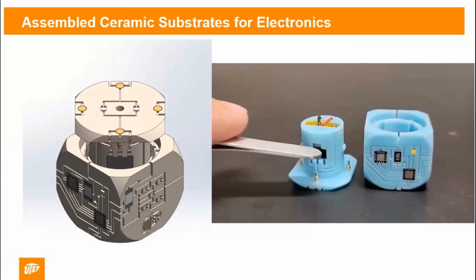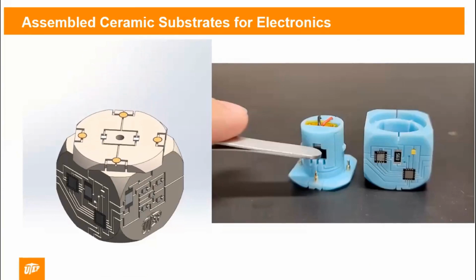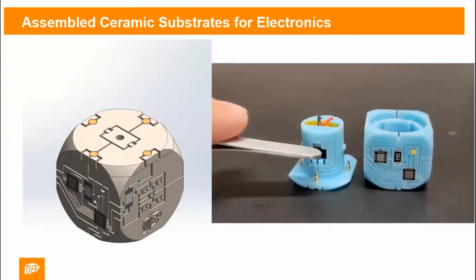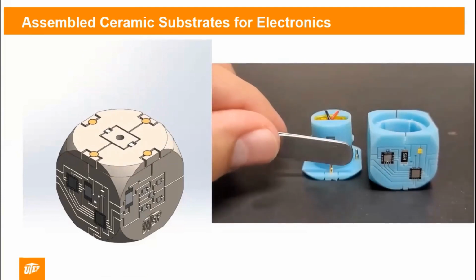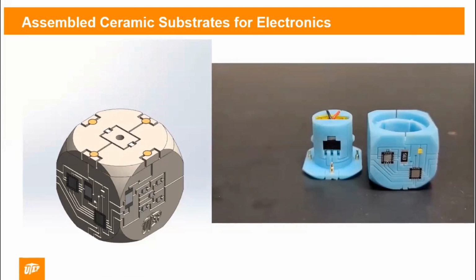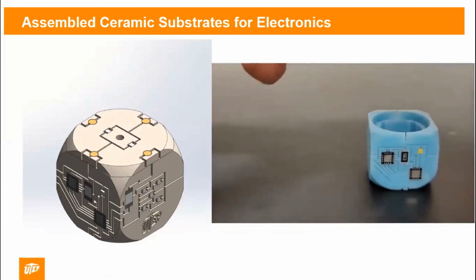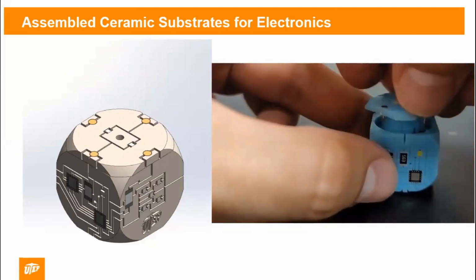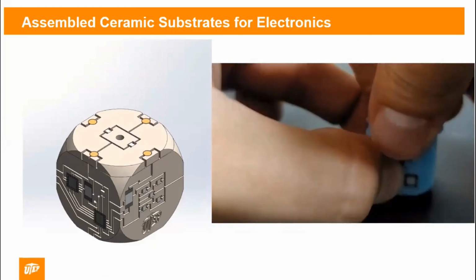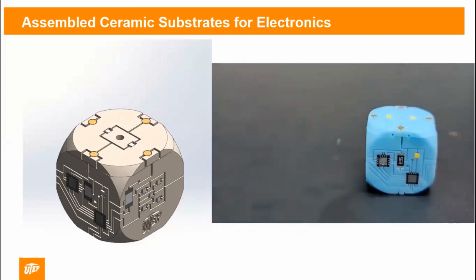So I'm trying to do another generation of this, and I want to do ceramics. And to do ceramics, I could print 2 parts and put a battery into them. When you print a ceramic, there's always a thermal post process. You have to put it at 1450 C for like 60 hours, cook out the plastic that was in the 3D printing. And when you do that, it shrinks. And obviously electronics aren't going to survive.